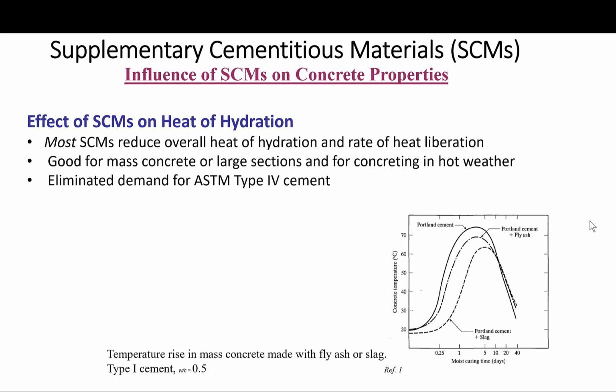Okay, on the heat of hydration, in general, most SCMs reduce the overall heat of hydration and rate of heat liberation. This is good for mass concrete or large sections, and for concrete in hot weather. The introduction of SCMs really eliminated the need for type 4 cement, the low heat of hydration cement, because this is a cheaper, more convenient way of reducing the heat of hydration.